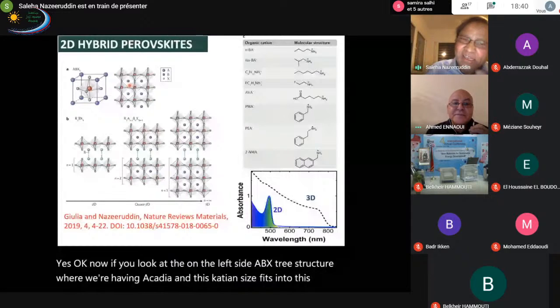Now if you look at this on the left side, the ABX3 structure, where we have a cation, and this cation size fits into this cavity. This is a typical size criterion, which is called the Goldschmidt tolerance factor. Within this Goldschmidt tolerance factor, the cation fits into this matrix. When the cation fits, the perovskite forms a three-dimensional network. So this is the one which we are looking at. And if you look at this three-dimensional network, on the bottom right side, you see the absorption spectral properties. It goes up to 820 nanometers.